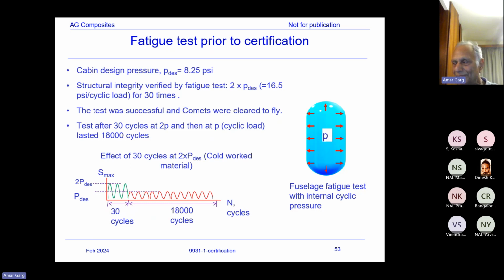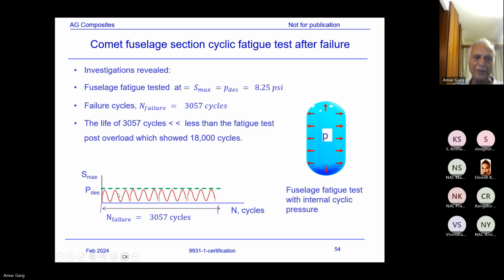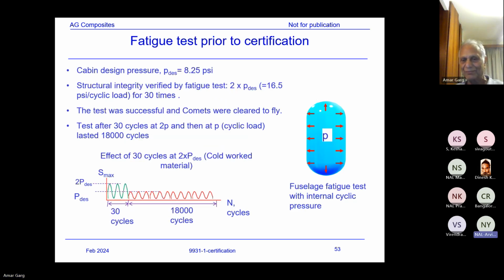Anybody has any answer? So when the fuselage was tested for double the pressure for 30 cycles and then tested at the normal design pressure, it lasted 18,000 cycles. But if it was not overloaded in the beginning, and tested at design pressure only, it lasted only 3,000 cycles. Any thought before I explain?